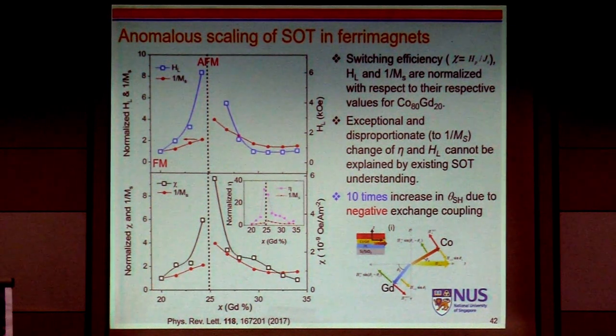If you look carefully now, this is the more cobalt-dominated region. And if you look at this side, this is the more gadolinium-dominated region. And it's not symmetric. If you look at this curve, this is very steep. However, in the gadolinium case, it kind of goes down and sort of saturates. And I think this is due to the response speed of cobalt gadolinium. When you inject angular momentum into this material, cobalt reacts first.